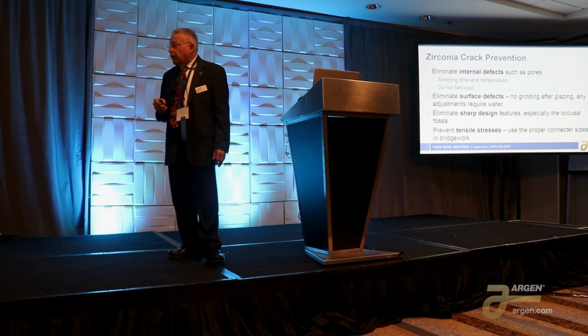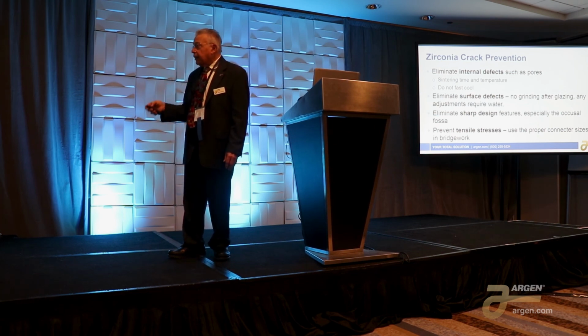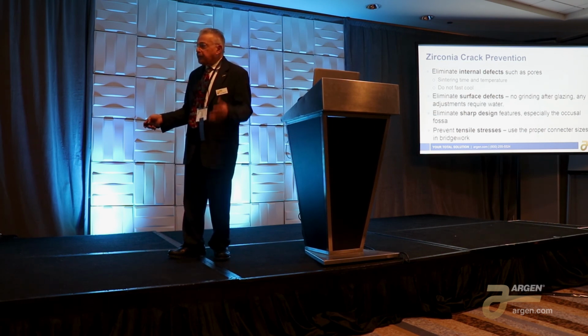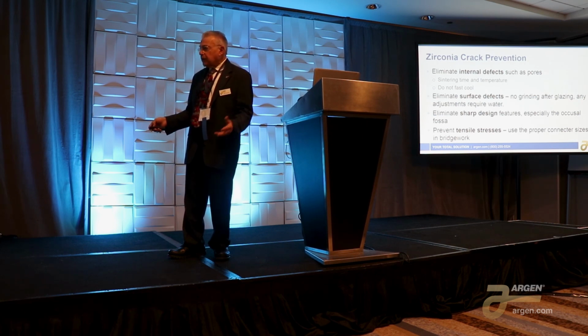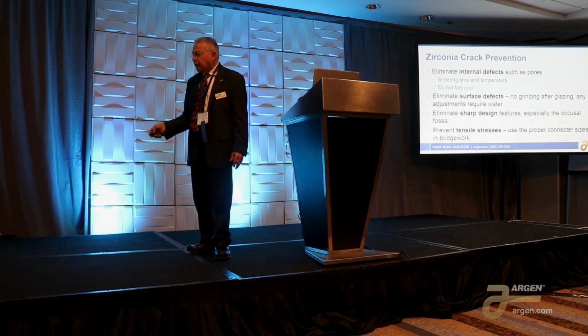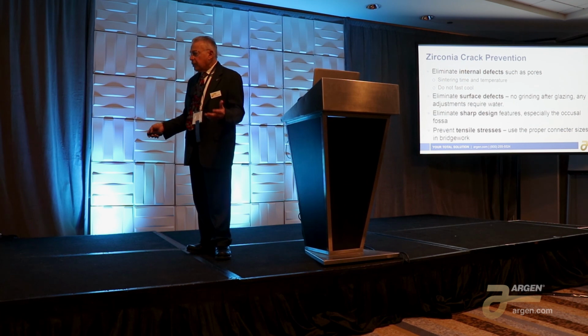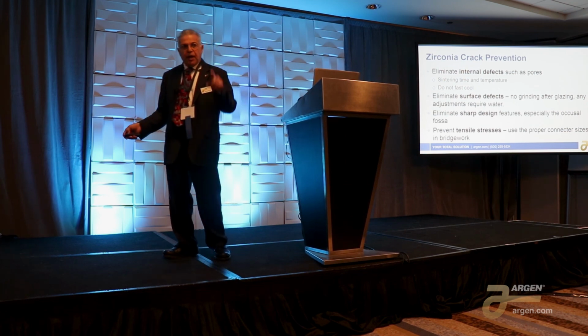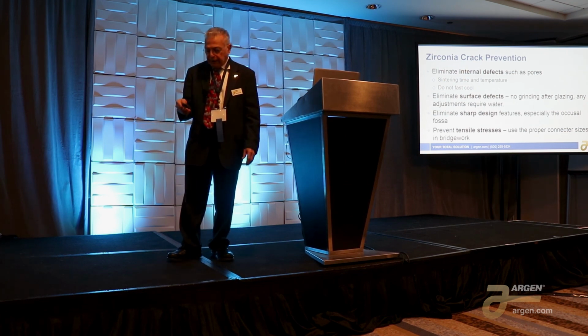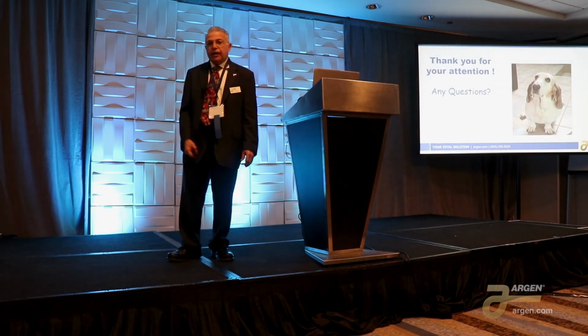So for zirconia crack prevention, eliminate any internal surface defects such as pores based on sintering temperature and time. Don't fast cool, that'll cause it to crack. Eliminate any surface defects, no grinding after glazing, and any adjustments require water along with the burr. Eliminate sharp design features, especially the occlusal fossa, and prevent tensile stresses. Use the proper connector sizes in bridge work, especially the height of the connector. Thank you very much.